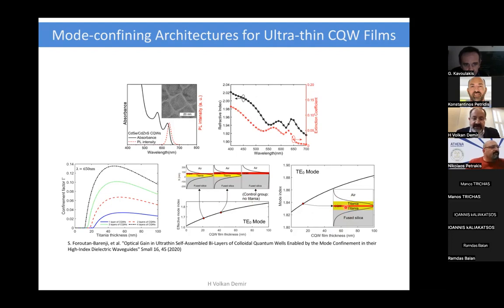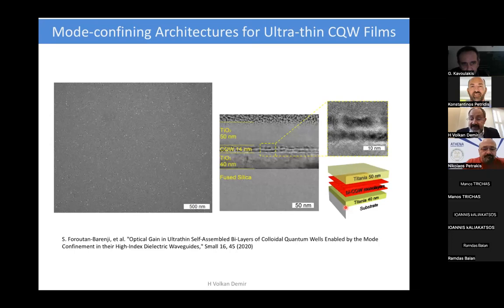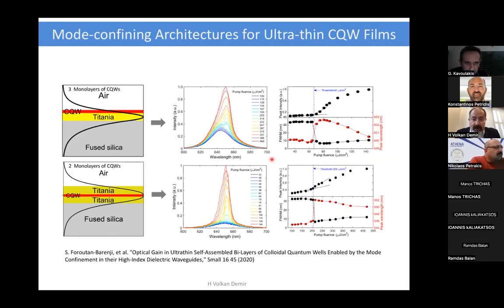And this was the way we approached having a thinner layer. And the thinnest in this case we achieved was, again, 2 monolayers. This is a 14 nanometer thick gain medium to observe, again, lasing behavior. I will spare you the details, but tell you this obviously requires careful optical design, numerical solution, and experimental demonstration to see this type of ultrathin gain material.